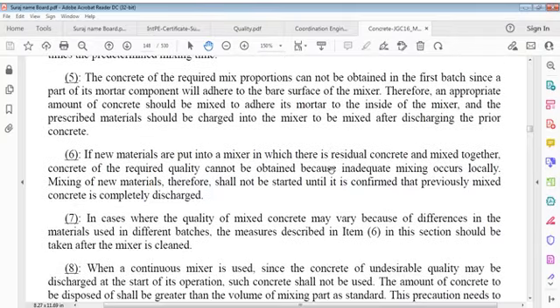Concrete of required mix proportions cannot be obtained in the first batch, since a part of its mortar component adheres to the bare surfaces of the mixer. Therefore, an appropriate amount of concrete should be mixed in to adhere its mortar to the inside of the mixer, and prescribed materials should be charged into the mixer to be mixed after discharging the prior concrete.